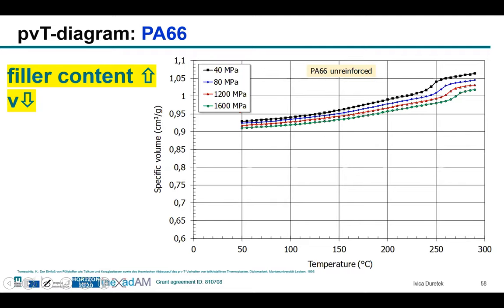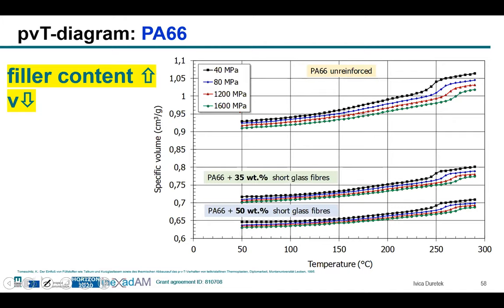Using the PVT measurement, you can determine very easily the influence of the fillers. In this case, the influence of the short glass fibers on the density or specific volume of polyamide. You can clearly see that with increasing content of the short glass fibers, the specific volume decreases. That means the density increases. But what's very interesting is that if you put the short glass fibers into the polyamide 6,6, the transition temperature is independent of the filler content.